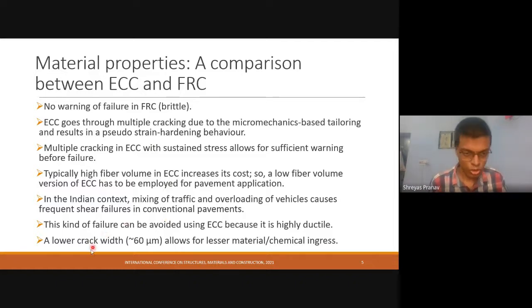And also one more benefit is that the cracks which appear in ECC are very different from the cracks that appear in concrete. Concrete typically has one large and wide crack, but ECC has multiple cracks, and those individual cracks are very fine micro cracks. So there is a lesser chance of material ingress. And as our first keynote session speaker, Dr. Kong, was specifying, it also possesses autogenous self-healing capability. So that is another benefit of ECC.